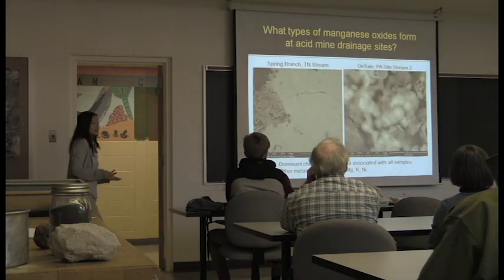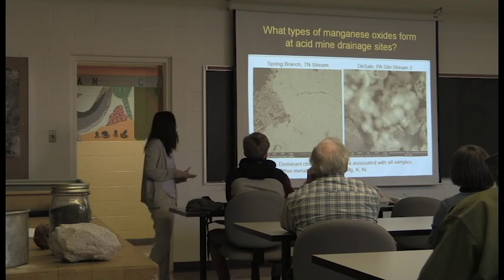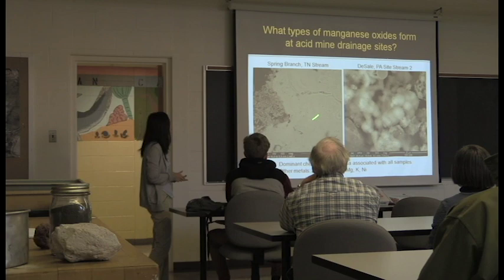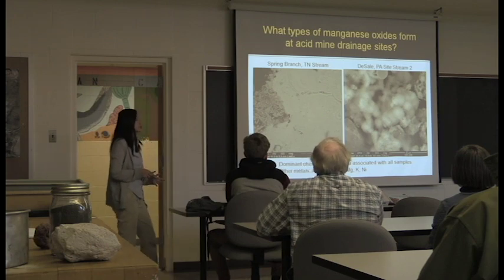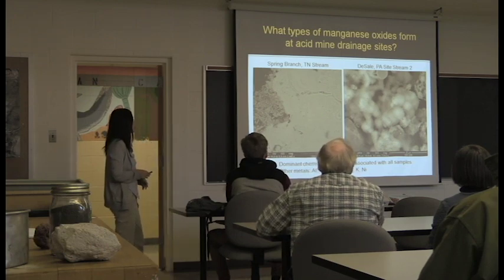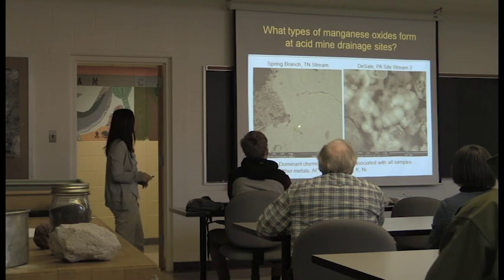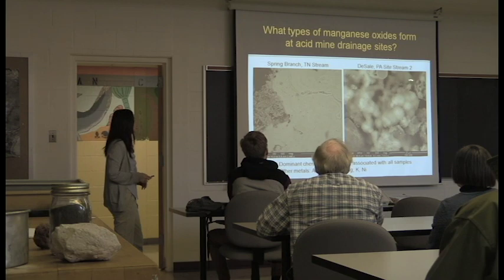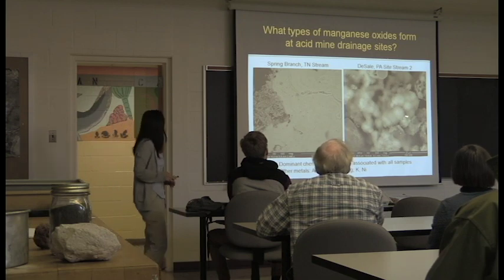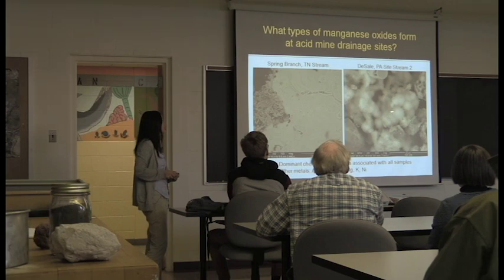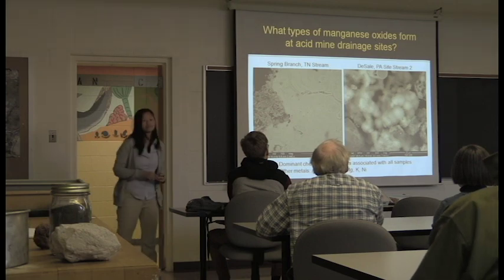I did some scanning electron microscopy on these, and you can see that these are images of the manganese oxides. And over here on the left is one of our limestone pieces that have been coated with the manganese oxide. So these beautiful layers are the manganese oxide layers on top of the limestone. Over here on the right is a sample from DeSale, Pennsylvania, from a stream. And the manganese oxides are these really tiny, less than 10 micron flakes that conglomerate into the fluffy spherules that you see here.